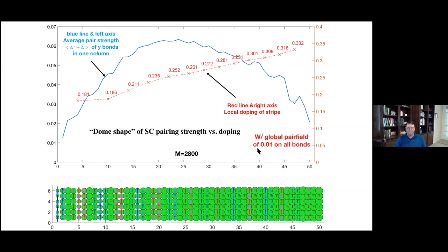This is with a global pair field put on everything, pretty small. We're working on making this even smaller. What you see when the system does this is that it goes through a regime where there are clear stripes, and then the stripes get more and more smeared out, but you still see the spin patterns for quite a while until, eventually at higher doping, the spin structure disappears. So there seems to be a smooth evolution of these stripes to more smeared out stripes as you go along, with a robust pairing response throughout. Sheng Tao sent me about 30 different slides like this that I could have shown, and I just picked out a couple of them. So this is very much work underway. We're trying to digest this and understand the overdoped regime.